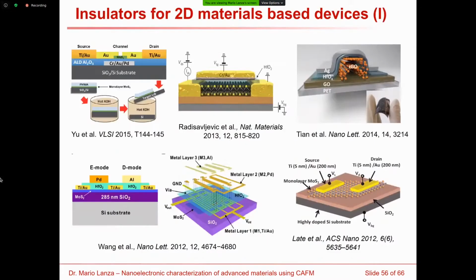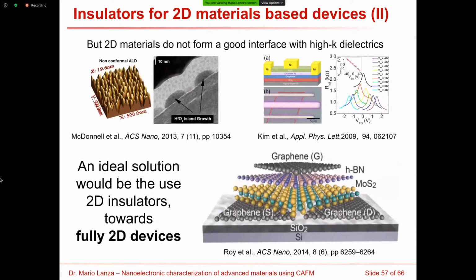So in this slide, I summarized some of the works on 2D materials-based field effect transistors in the literature, some of the most impactful works, and you can see something interesting. Most of them use hafnium oxide, high-K dielectrics, aluminum oxide, or silicon oxide for these studies. However, this is an important problem because the interaction between traditional three-dimensional dielectrics and the 2D material is very problematic, because the 2D material doesn't have dangling bonds, and therefore we cannot form a conformal coating. So basically what you get if you try to deposit, for example, hafnium oxide on molybdenum disulfide is some dielectric islands that are confined at the defects in the 2D material.